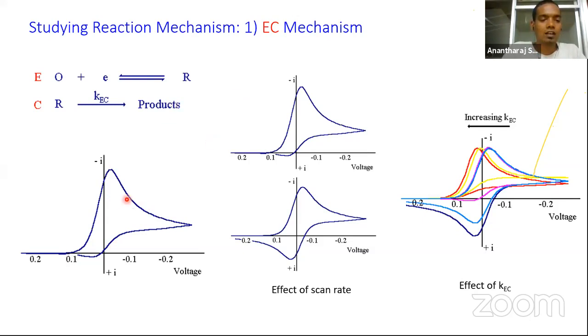This you can actually confirm by just varying the scan rate. In the case of a sufficiently higher scan rate, when you don't have sufficient time for the reduced product to form further chemical products, you will actually see the oxidation peak. But when you perform the reaction at a very slow scan rate, you are letting the reduced product get converted into the desired products through chemical reaction, so that you are not seeing any oxidation peak. So just by varying the electrochemical reaction scan rate, you can confirm whether the reaction mechanism is following the EC mechanism or not.